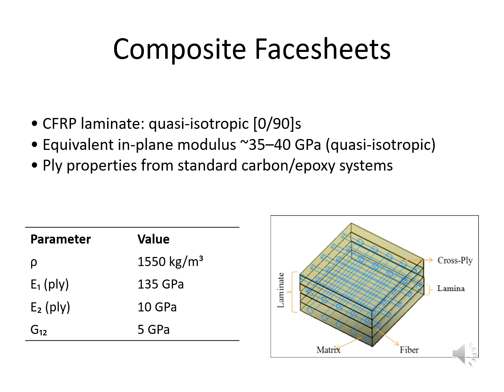These methods allow us to evaluate different failure modes, such as fiber tension, fiber compression, matrix cracking, and shear failure at the laminar level. By combining the laminate definition with a homogenized core, we obtain a fully consistent model of the sandwich cross-section that supports both structural and thermal loading.